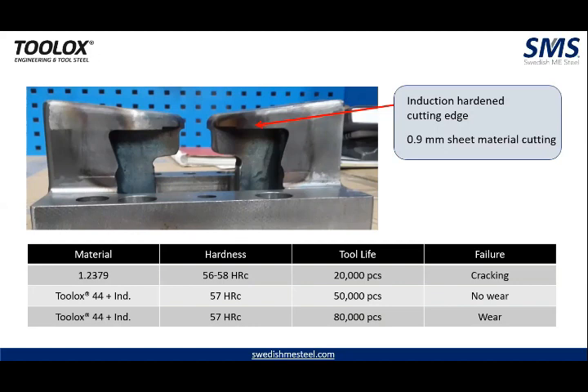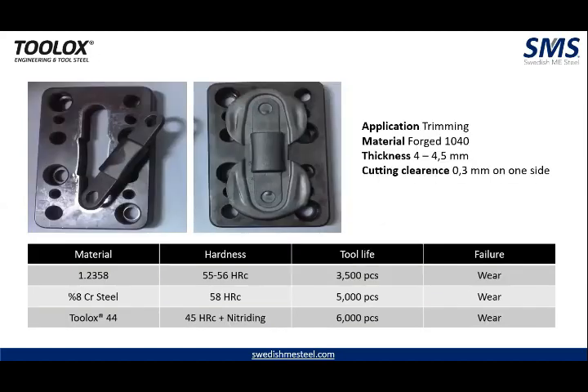So again, I reiterate, any issues that you have with cracking with any of your current material, then Toolox 44 is an absolute friend for you. Again, trimming of forged material, 4 to 4.5 mm thickness. Even expensive metal were used. They had faced an issue of wear. Compared to that, Toolox 44 plus nitriding gives you much better life than your regular items.